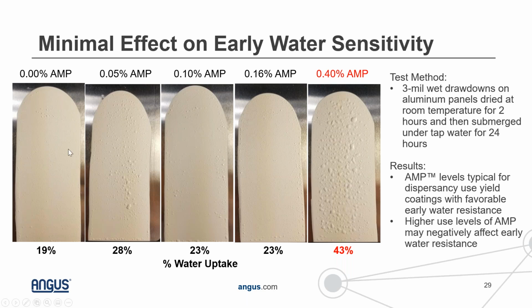You can certainly see that just in the panels themselves, the control has no evidence of blistering. There's a little bit of blistering in the sample with 0.05% AMP, but it's pretty minimal, especially for 0.1 and 0.16% AMP on total formulation weight. The water uptake is around 20%, which is similar between the control and the samples with AMP.